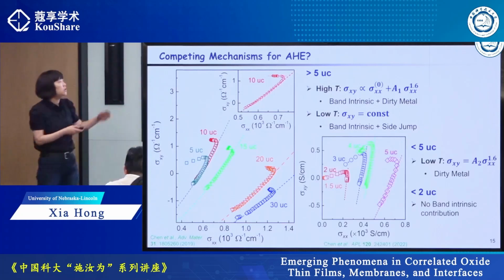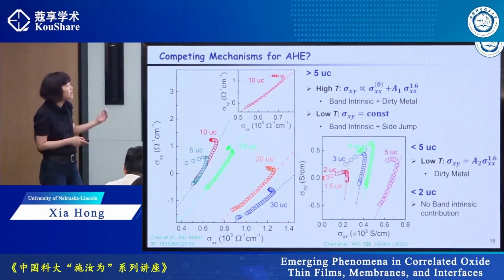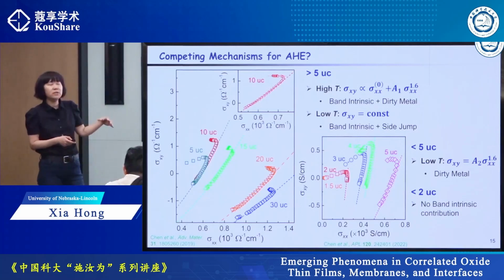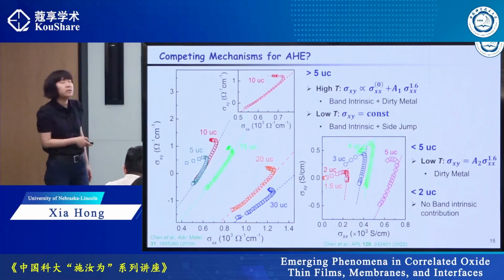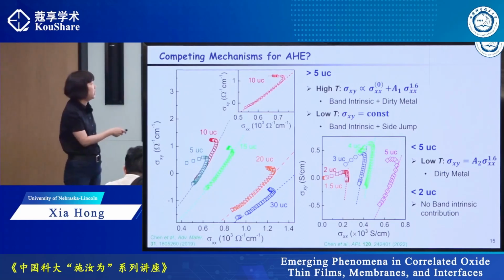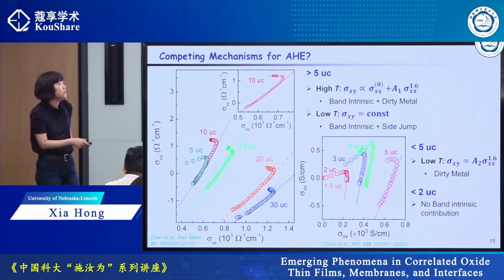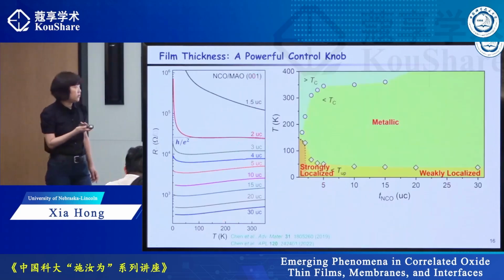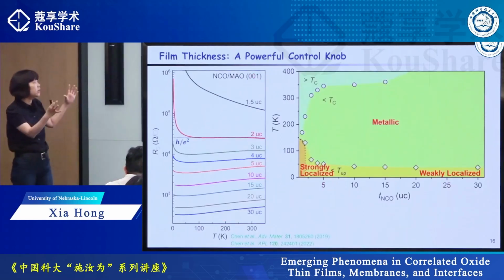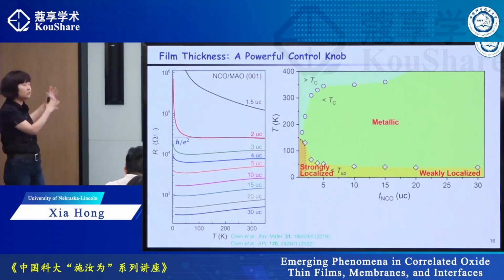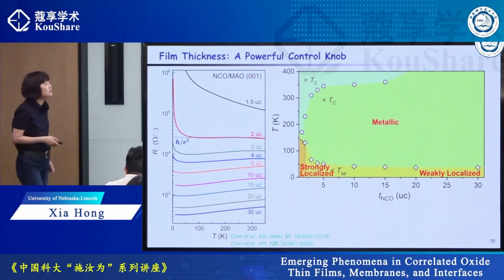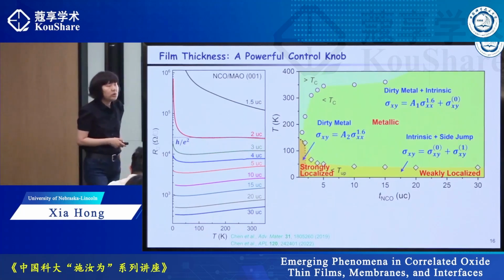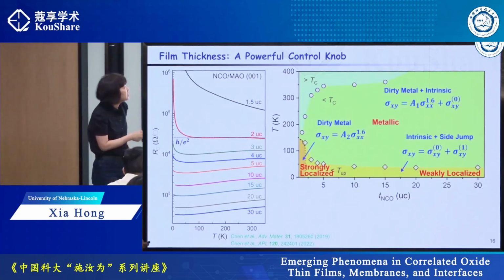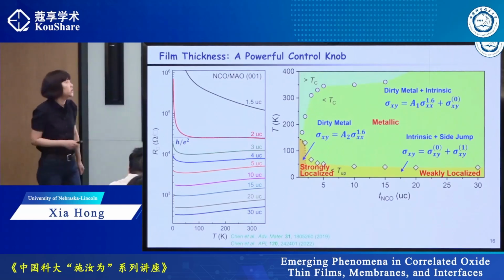If you push it to even thinner films, you can see that gradually, when the sample conductivity becomes lower and lower, close to the metal-insulator transition, this band intrinsic effect actually disappears. And for both high and low temperature, you can use this simple scaling behavior to describe it. And we try to actually compare the anomalous Hall resistivity with the metallicity of the sample. Indeed, we can well describe different phases, what kind of anomalous Hall you would expect.